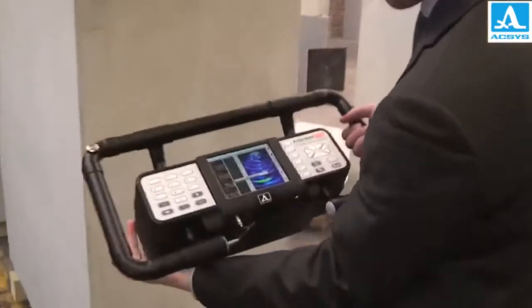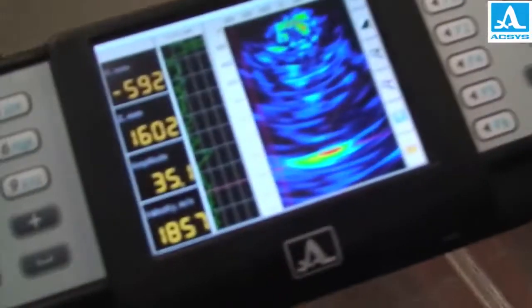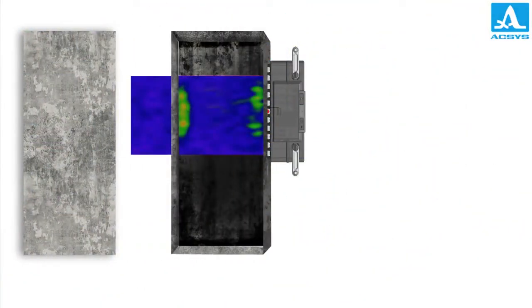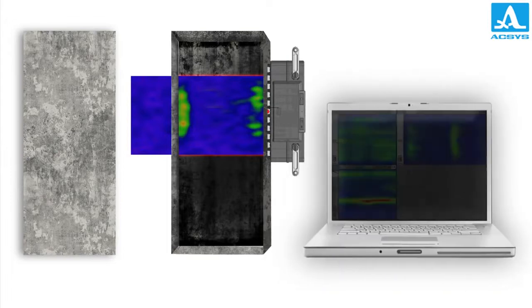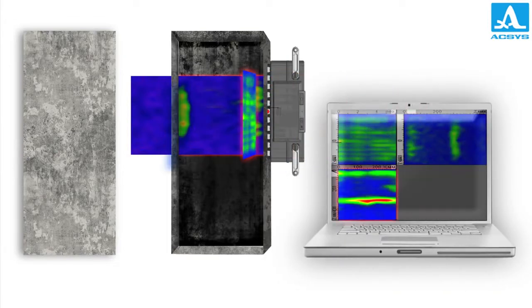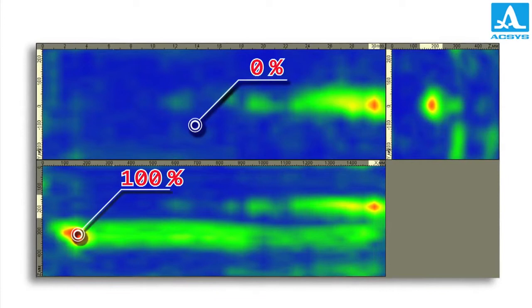The test results are shown as a typical B-scan, a cross-sectional image of the area below the antenna along the plane parallel to the longitudinal axis of the antenna. The image can then be further post-processed and analyzed along any given plane using a personal computer. The image showing the internal characteristics of the test sample is visualized as a perspicuous color map.